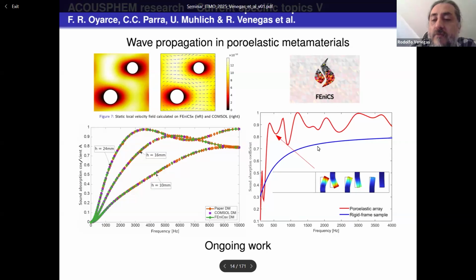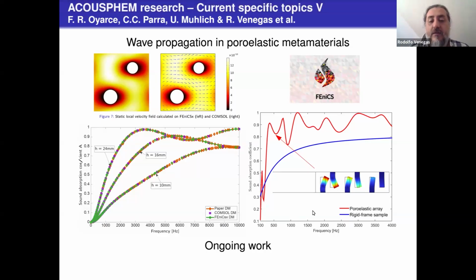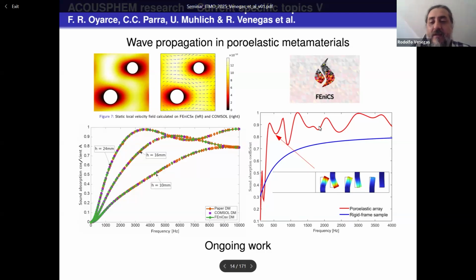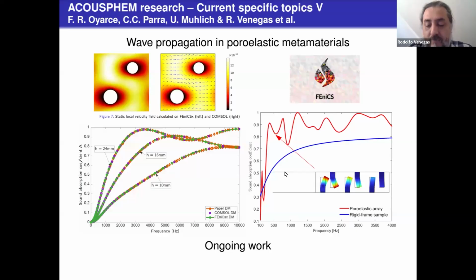So in blue we have the sound absorption coefficient of a rigid frame porous material that is very thick, about 10-12 centimeters, and in red is the sound absorption coefficient of these poroelastic elements that are constrained and are arranged as we can see here. So just by rearranging this material and constraining them locally, we can improve significantly the sound absorption coefficient with very rich behavior due to inner resonances of these local elements. This is ongoing work, and that is going quite well. So we are very confident that this is going to provide us with a very interesting line of work.